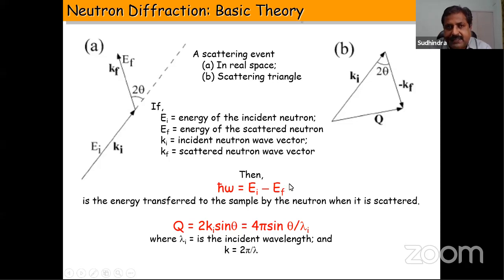When we talk about diffraction, we are talking about elastic scattering, which means that E_i is equal to E_f. The incident energy and the scattered energy of the neutrons are the same. Therefore, in this case, the scattering wave vector can be written by this equation, which is basically Bragg's law in reciprocal space. Our scattering wave vector is 4 pi sine theta by lambda. And the constructive interference, as in light scattering experiments, can be understood in terms of neutrons by this condition. If this condition is satisfied, we get a diffraction.